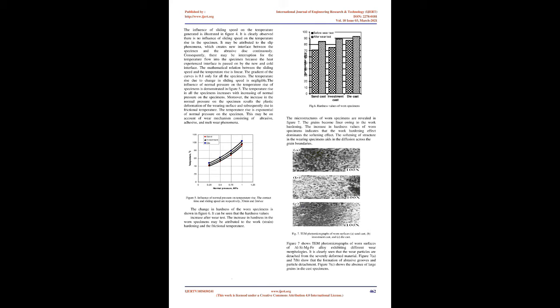Wear tests include the measurement of weight loss using an electronic weighing balance with accuracy up to 0.1 mg, temperature of the pin using a thermocouple, and friction force with a data acquisition system. The mechanical properties and metallurgical morphology were investigated to evaluate the wear behavior of these alloys.